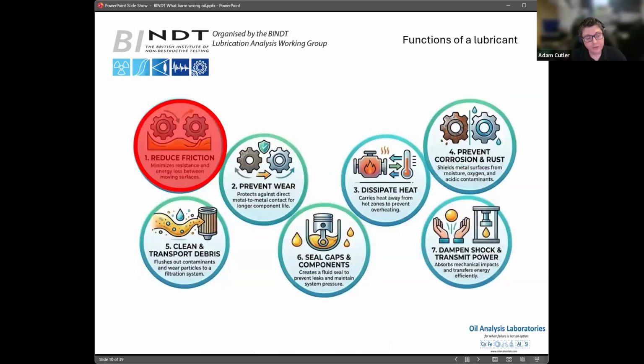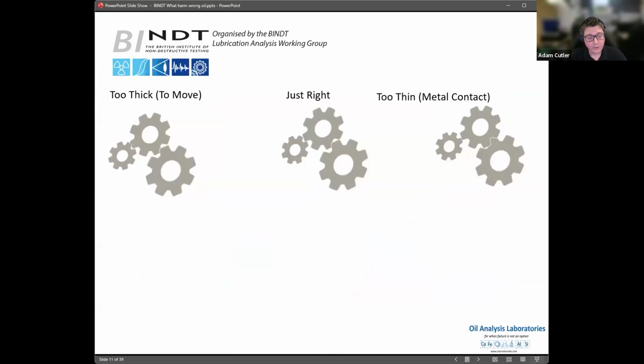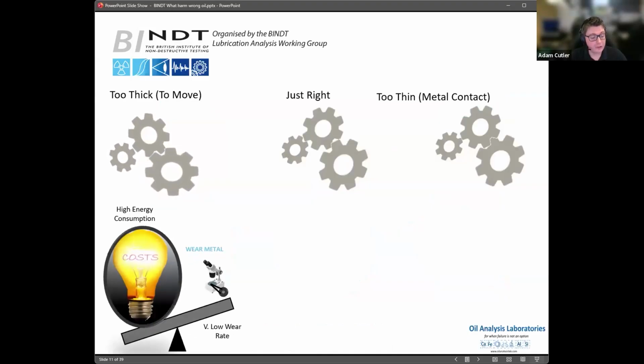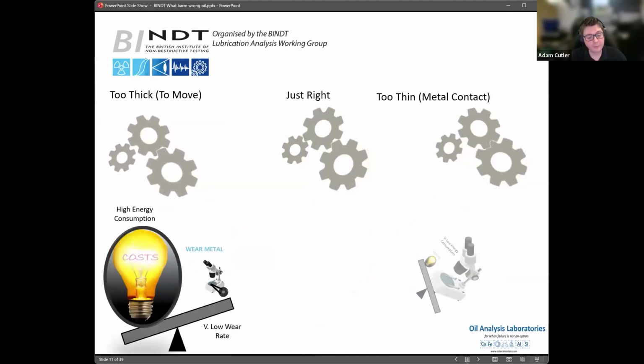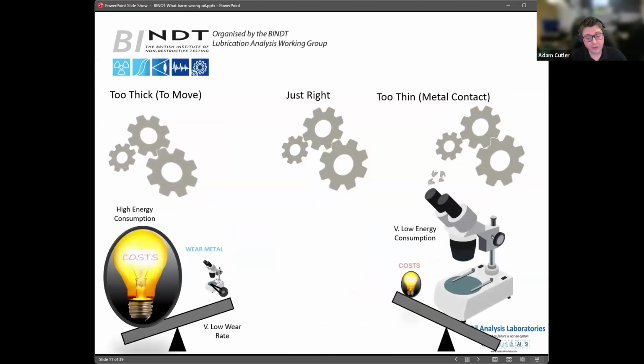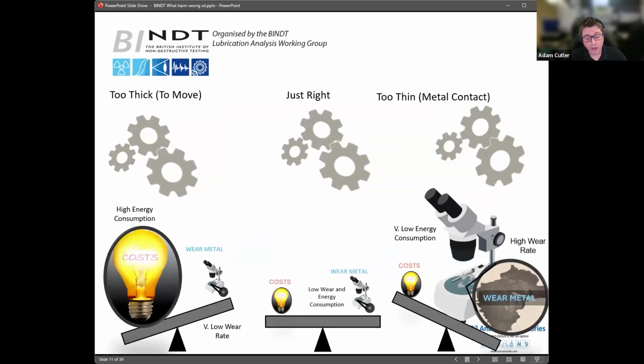But can it be too thin? This actually brings us into our next area, which is preventing wear. If something is too thick, as I highlighted before, you have high energy consumption, but you get a really good film thickness. In contrast, if something is too thin, you get better fuel economy, at least at the start, but you get more risk of metal-to-metal contact. So you don't want an oil that is too thick or too thin. You want this Goldilocks zone of something just right, thick enough to give surface separation, but not so thick that it leads to increased drag and increased energy consumption.